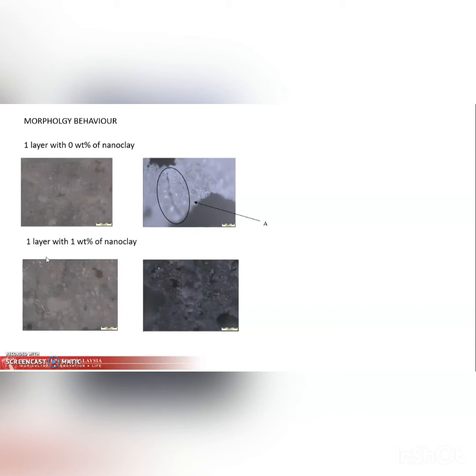Now we continue with 1 layer with 1% of nanoclay. The surface of the geopolymer composite shows shrinkage because the water evaporated. So after the fire retardant testing, it can be seen that the sample agglomerated since there is 1% of inclusion of nanoclay. The agglomeration helped to reduce the effect of char because it takes a longer time to burn compared to the sample with 0% of nanoclay.